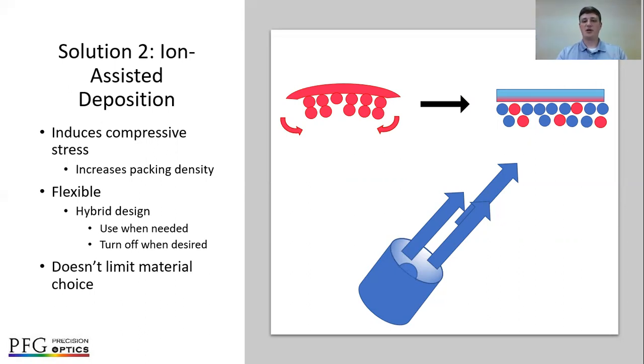Furthermore, ion-assisted deposition doesn't limit your coating material choices, whereas sputtering has a very limited database of coating materials available. Ion-assisted deposition still allows you to use almost any coating material you like because it's simply an enhancement. And so option 1 of coating material choice is still in play with ion-assisted deposition.